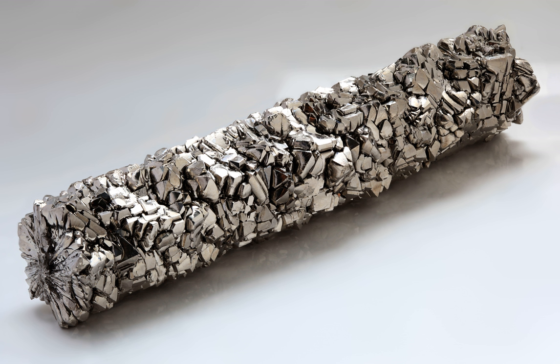To produce the titanium 4 chloride required by the Kroll process, the dioxide is subjected to carbothermic reduction in the presence of chlorine. In this process, the chlorine gas is passed over a red-hot mixture of rutile or ilmenite in the presence of carbon. After extensive purification by fractional distillation, the titanium 4 chloride is reduced with 800 degrees Celsius molten magnesium in an argon atmosphere. Titanium metal can be further purified by the van Arkel de Boer process, which involves thermal decomposition of titanium tetraiodide.